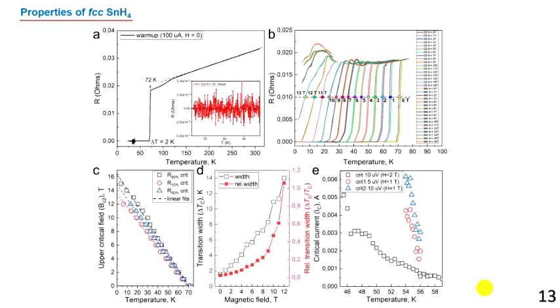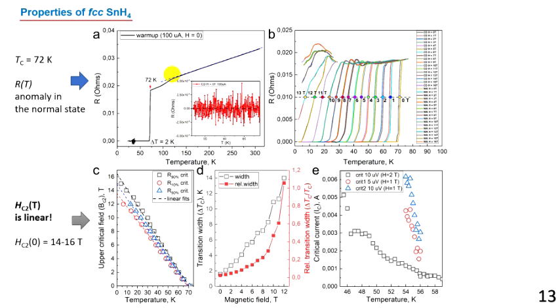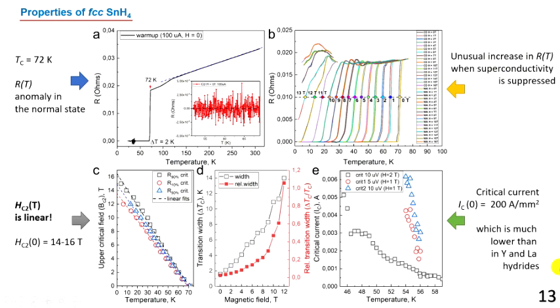Okay, and after that, we investigated transport properties of SnH4. And first of all, we noticed that this compound demonstrated a superconducting transition at about 72 kelvins, but at temperature around 120 kelvins, we can see a kink in the temperature dependence of electrical resistance. When we investigated the behavior of this compound in external magnetic field, we found that actually the upper critical field is linear, and this is serious deviation from the WHH model, which is commonly used for conventional superconductors. There is unusual upturn feature, unusual increase in the electrical resistance when superconductivity is suppressed by a strong magnetic field. You can see it here on this diagram. And finally, we investigated critical currents. Results show that the critical current in this compound is pretty small.